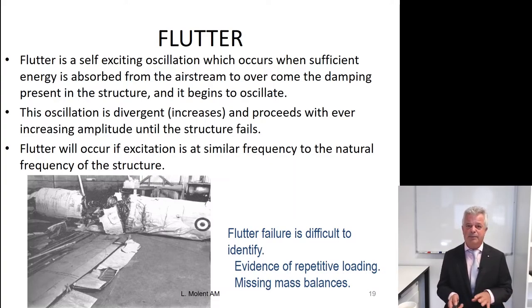From an accident investigation point of view, flutter is kind of difficult to detect. This is a Jindivik that had crashed due to flutter, and some of the evidence that we saw was what looks like crimpling of the fuselage. That's interesting. That's due to multiple cycles of something. That's strange. And the other thing was the lead mass balances on the control surfaces, used to trim the control surfaces. They were missing, okay? Hang on. Something of high oscillations occurred here to lead to this failure. Flutter. And we're able to prove that.